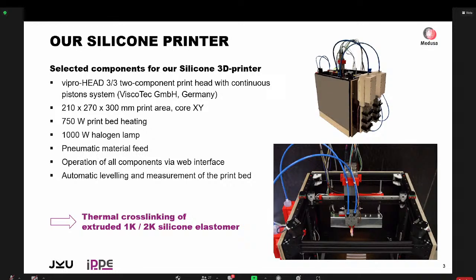Dragon Skin, the commercially advertised silicone for this purpose, is not cross-linking without heat at all. That's actually one of the disadvantages of this Dragon Skin material, that when you leave it in this system, the component B actually starts cross-linking. But with using existing materials from the market, you don't get the details of the consistency. So the goal would be to get materials that don't have that. And these traditional silicones are usually very slow in reactivity.